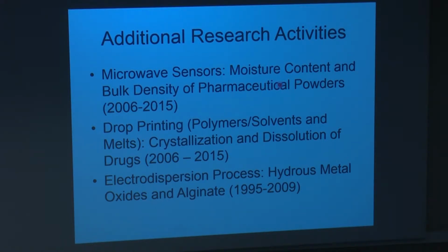And then we did drop printing of pharmaceuticals from solutions of polymers and solvents, as well as dissolving the pharmaceutical in melts and then looking at the crystallization and the dissolution of the drugs. This work was done between the years 2006 and 2015. And the final thing that I worked on from this list is the electrodispersion precipitation process, where we were interested in making hydrous metal oxides and also calcium alginate microspheres, where these calcium alginate microspheres were used to encapsulate proteins. This work was done between 1995 and 2009.